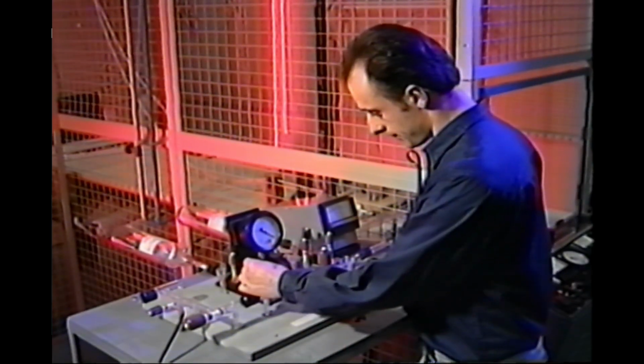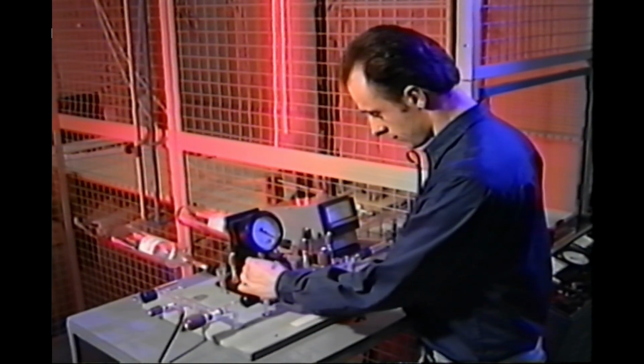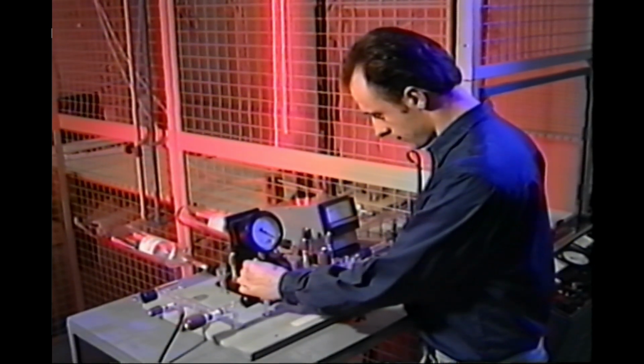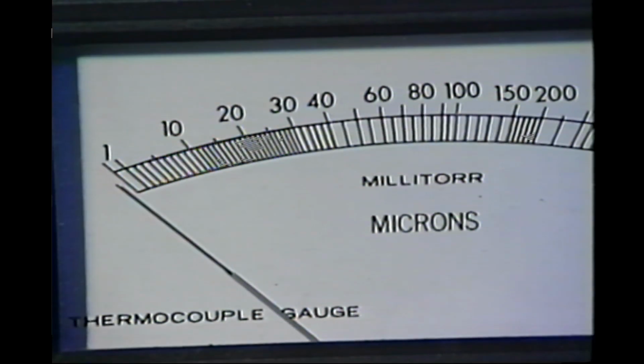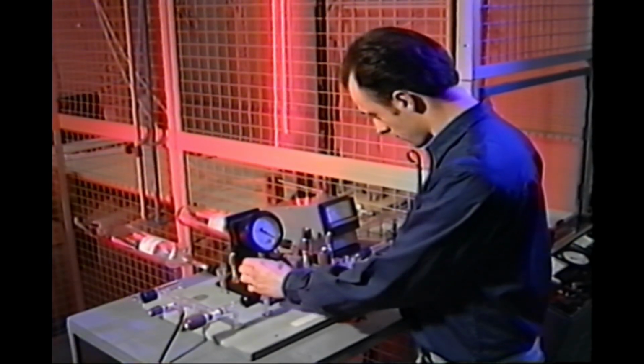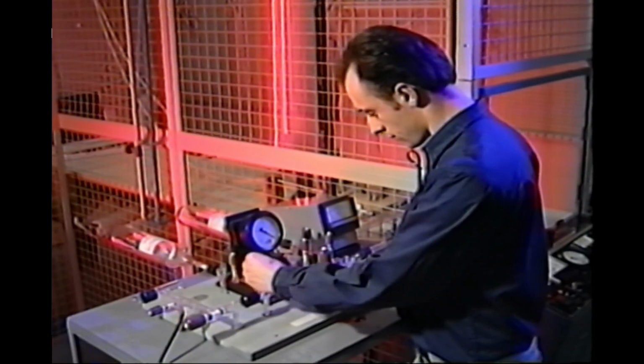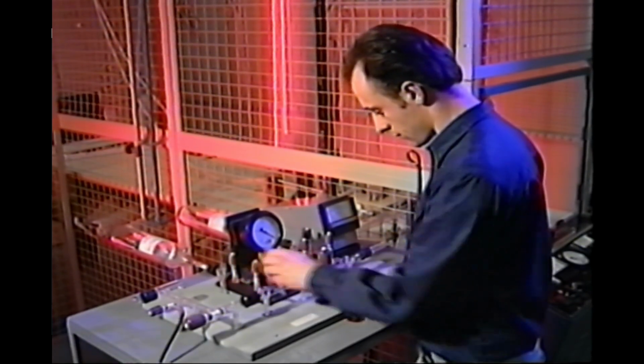Fully open the first stopcock of the rare gas to be introduced to evacuate any contaminated gas in the sidearm between the stopcocks. When this gas has been pumped away and a vacuum reading of 1 micron or better has been re-established, close the small stopcock. Close the main stopcock.